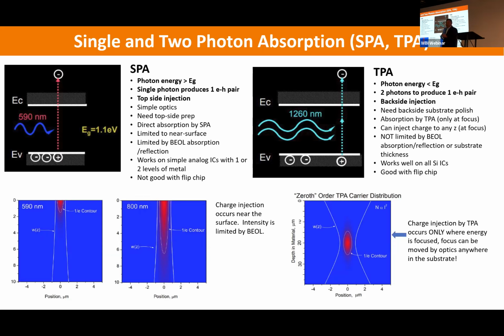What's the benefit of this? Why do we go to this trouble? Because in single photon, if I were to irradiate a sample, most of these electron hole pairs will be generated at the surface of the device. In the two photon, or single photon, we go from 590 nanometers, 800 nanometers goes a little deeper, but not deeper than 6 microns. In the case of a two photon system, we can penetrate up to 20 microns, depending on the energy, into the device, and I can position exactly within the volume where I want that energy to be generated, especially where I want that electron hole pair to be generated, or in other words, where I want that single event to happen in the device. So that's unique about this two photon absorption system.